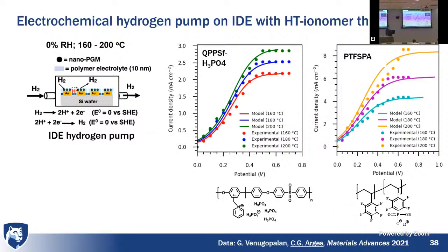It can block gas transport. We see we have a lot more polarization. We get lower limiting current densities. Here with the phosphonic acid ionomer, we get less polarization and higher limiting current.